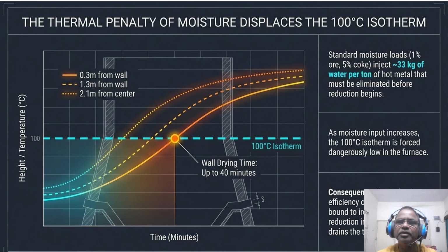Why does this matter? Because reduction cannot begin until the water is eliminated. This delay causes gas reduction efficiency to plummet. Oxygen remains bound to the iron longer and the thermal reserve in your lower furnace is drained to compensate for the lack of stack preparation. We are effectively moving the work of the stack into the hearth, which is a recipe for a cold furnace. Detecting these moisture swings is one thing, but reacting to them without a plan often leads to a dangerous and very impactful operation trap.